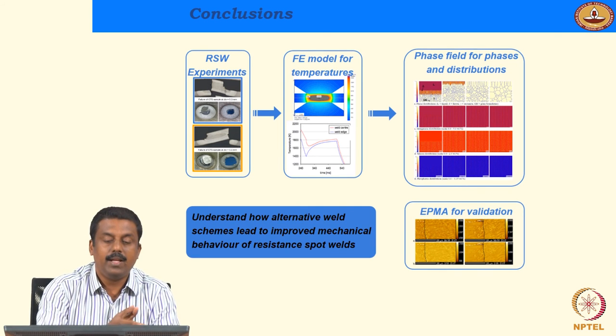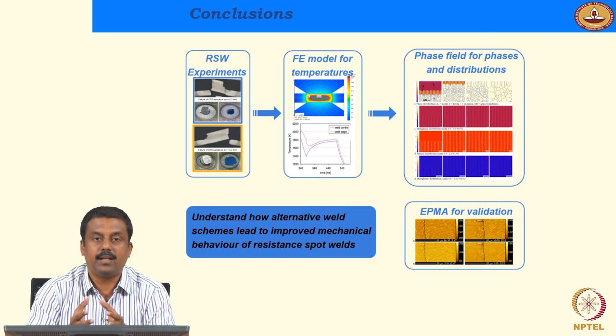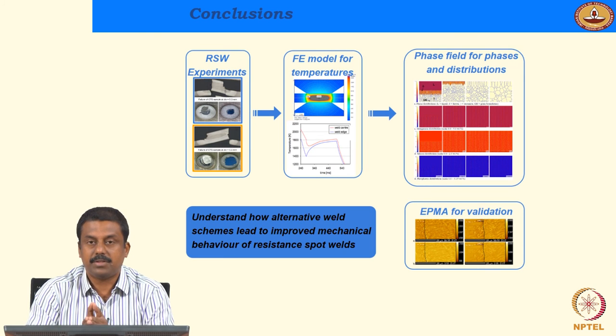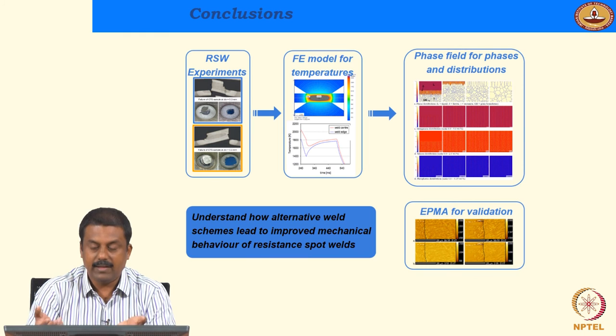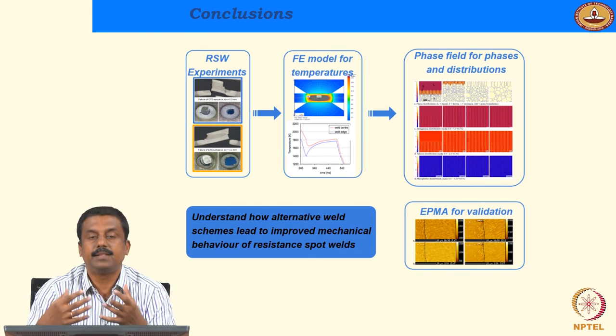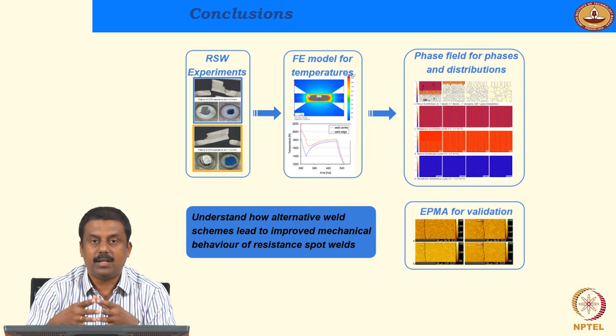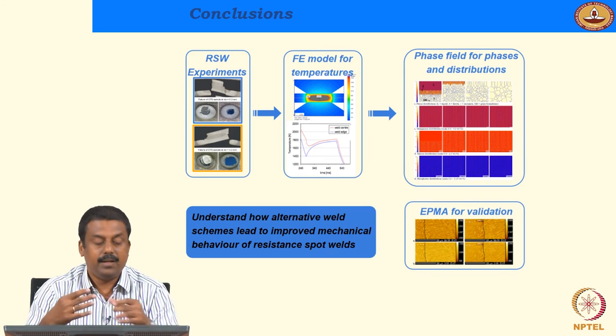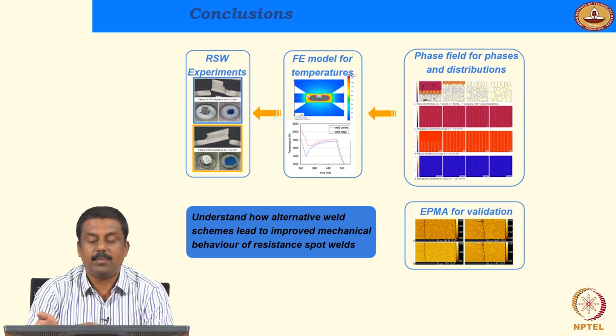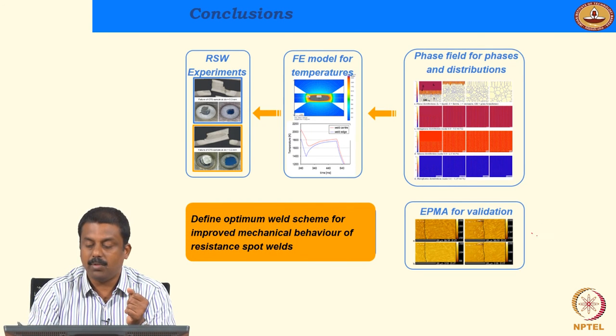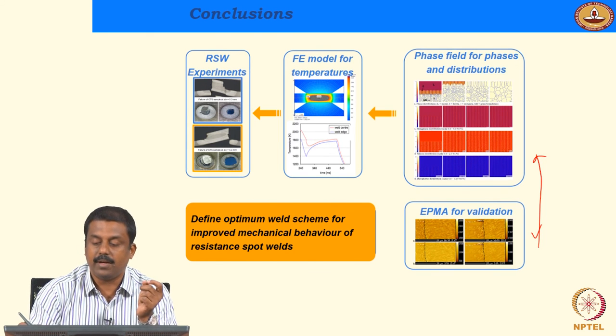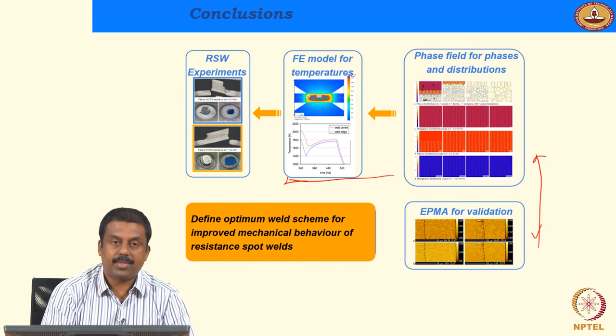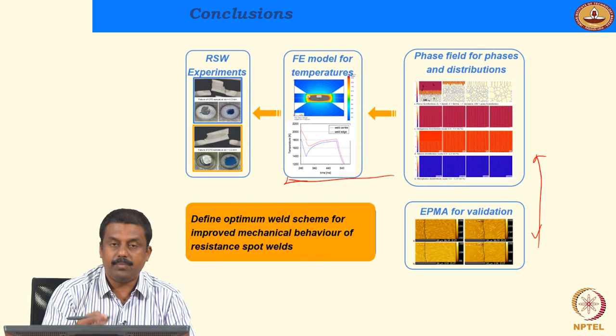is we do a resistance spot welding, okay, and then you look at the thermal cycle you are going to apply, then analyze the microstructure and investigate why the weld is failing. But now what you need to understand is, you first make yourself comfortable with the physics, the metallurgy of these advanced iron steels during welding. So once you understand that, instead of playing around with the welding parameters to get better mechanical properties, you know what microstructure you want, what segregation, how homogeneous the elemental distribution should be, and then we can understand the microstructure evolution, and which thermal cycle can give you this homogenization, and subsequently you can have a thermal cycle predicted